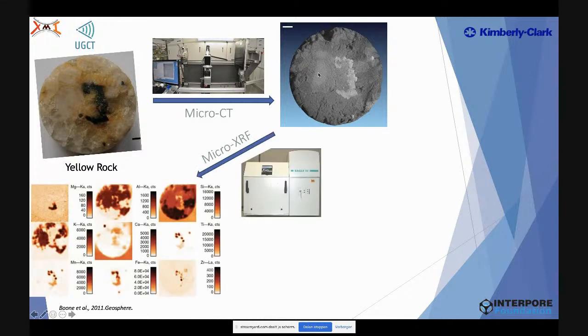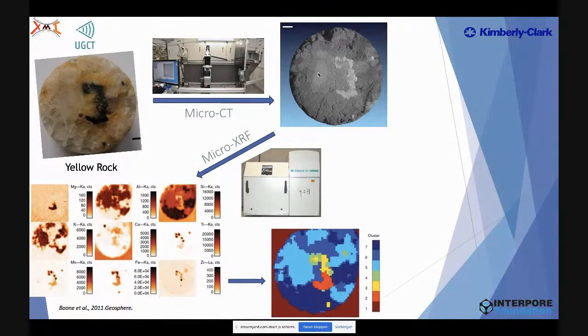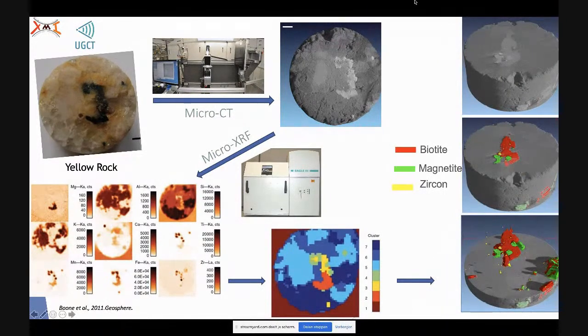So we then put this in a micro XRF system. We did elemental mapping of the surface. We clustered this information and then combined this with the CT data. This allowed us to combine chemical information with the gray values and get a kind of estimate of where minerals were positioned inside our sample, but based on some estimates. Of course, it's not so ideal that you have to put your sample in different systems.